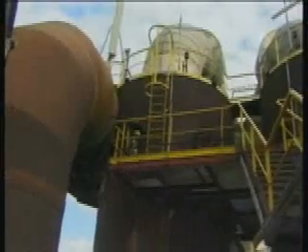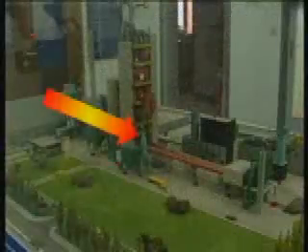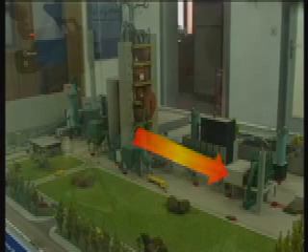While being poured from the top of the tower, it meets hot gases and goes from a temperature of 300 degrees Celsius to 1200 degrees Celsius before reaching the bottom. Midway in the tower, we have the precalciner, where the temperature will be about 800 degrees Celsius. Upon exiting the tower, the flour will be at 1200 degrees Celsius and will increase to 1400 degrees at the end of the furnace. The clinkerization phase will be performed in the furnace.